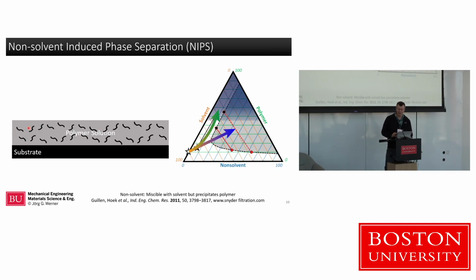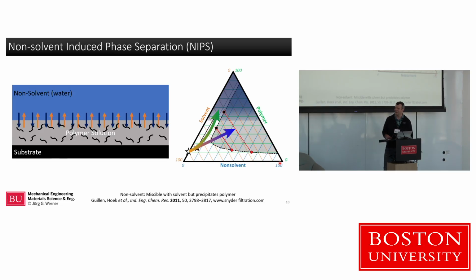You take a polymer solution, a liquid, you spread it onto a substrate, like putting paint on the wall. And then what we do is we make use of the fact that the polymer solution and the polymer itself might have liquids that it doesn't like. We call those non-solvents, which cause this polymer to precipitate. So we take our wet paint on our substrate and immerse it into a non-solvent. That's often water. Most polymers don't like water.